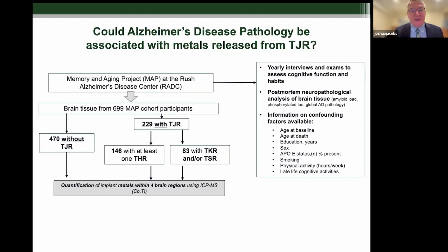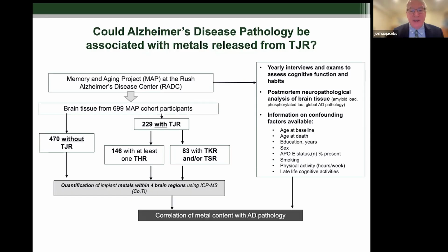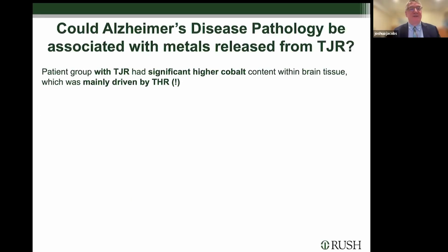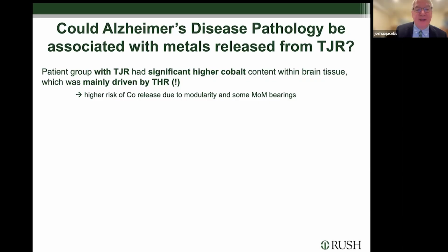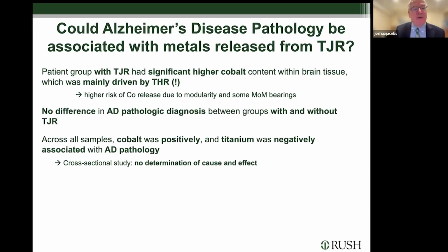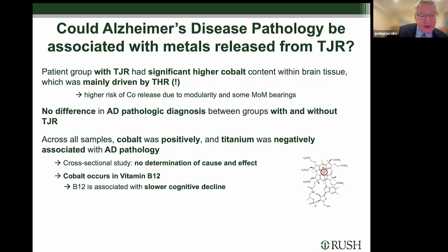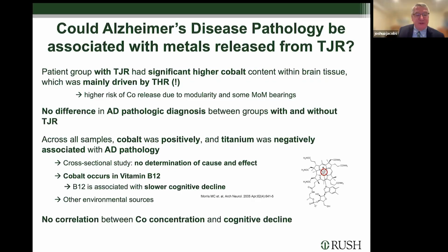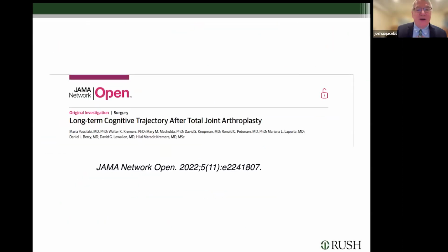So we correlated the patients that had joint replacements with findings of Alzheimer's disease, measuring metal levels in the brain and looking at Alzheimer's histology. What we found was that patients with total joint replacements had significantly higher cobalt within the brain, mainly driven by total hip replacement. Across all samples, cobalt was positively correlated with Alzheimer's disease pathology. Fortunately, there was no correlation between cobalt and cognitive decline. So we're left with this question: what impact do these metals have on the brain long term? We don't know. Hopefully, they're not causing cognitive decline, but they do get to the brain, and this is an area we need to understand in far more depth.